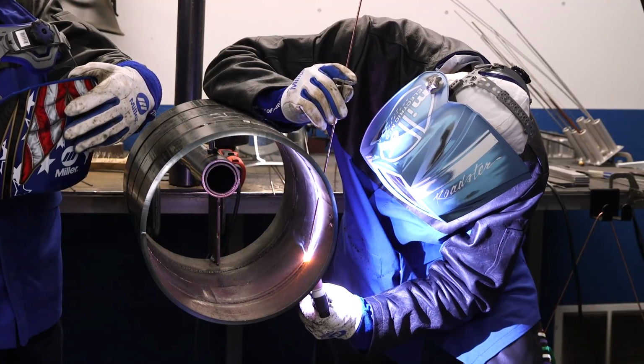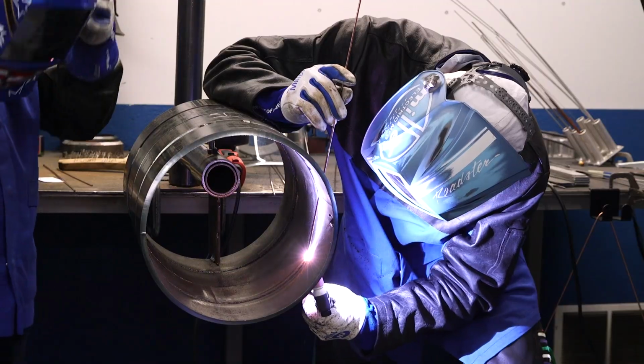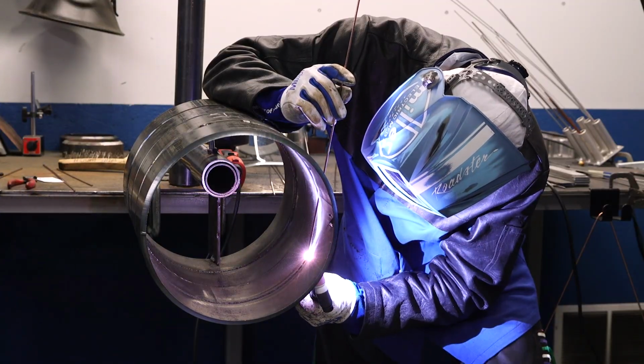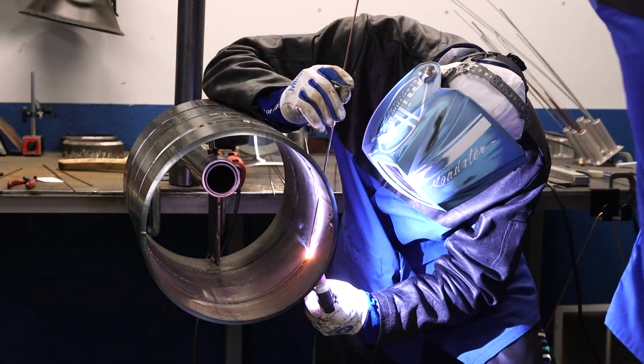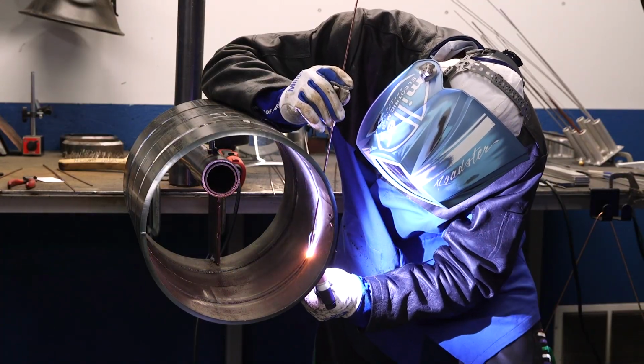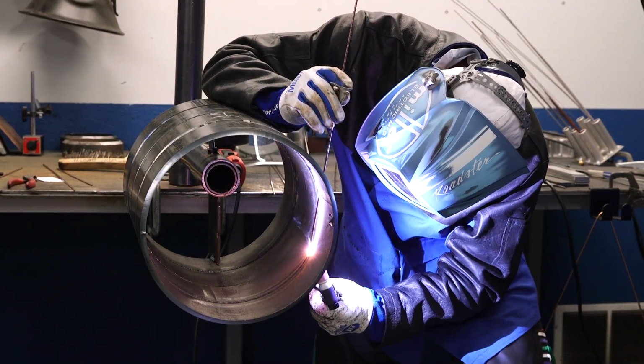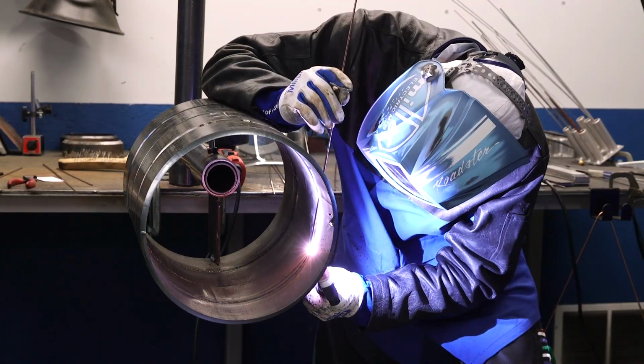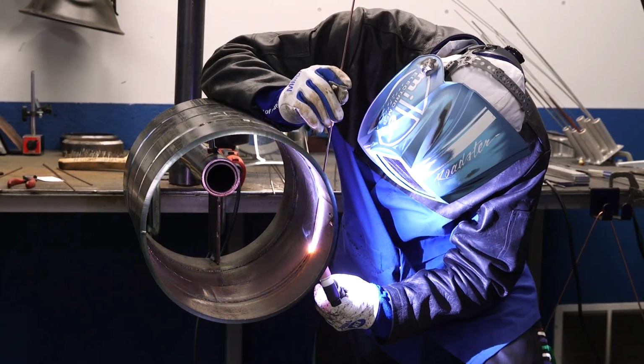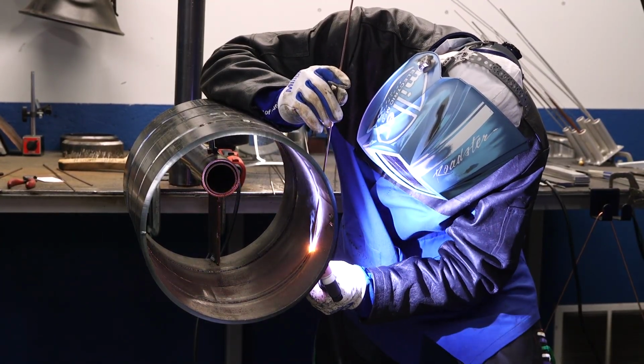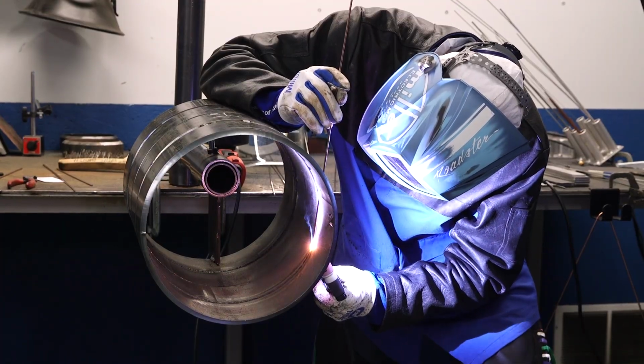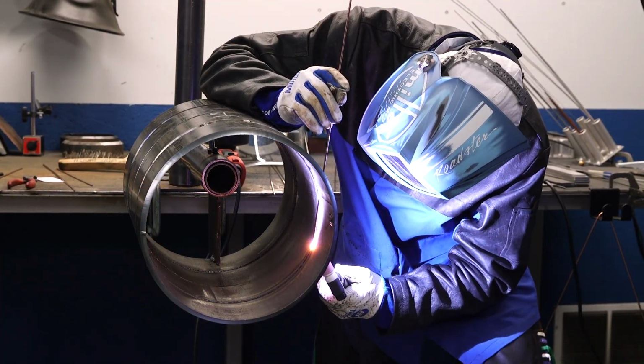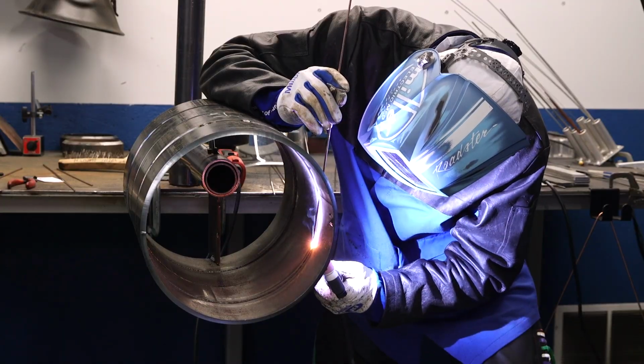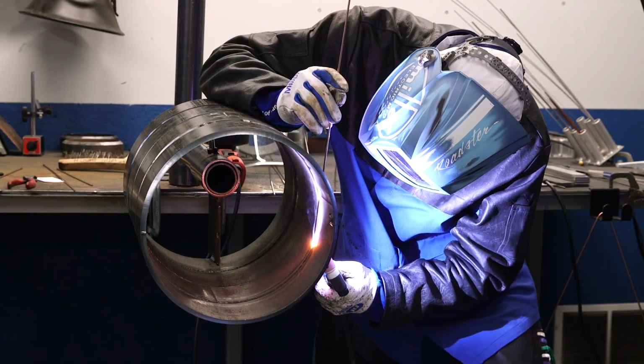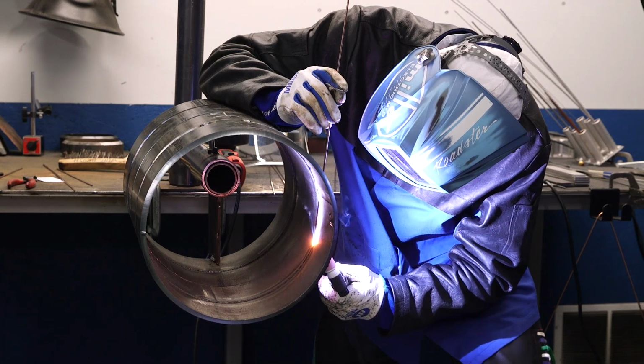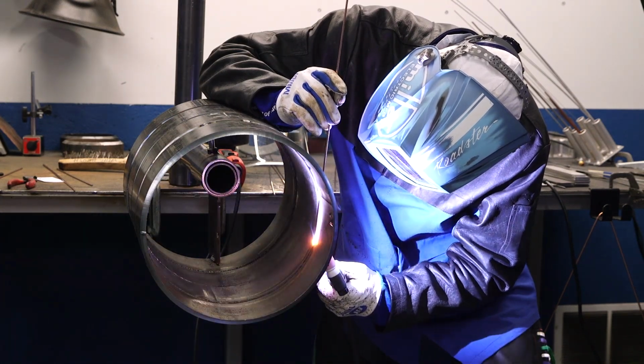How many amps does it say on the remote there, Dakota? You are at... So might get you just to turn me down a little bit just to have a little bit more control. 99 amps will go, there's 97, maybe a little bit colder. 96, 95. Thank you. Yeah, because essentially what I'm watching here is I had Dakota turn me down a little bit because I can see how the puddle is solidifying from when I move from bevel tip to bevel tip. And I just wanted it a little bit colder so it would solidify that puddle a little bit when I move away from one of the bevel tips. And that way I don't get a heavy root pass or nothing.